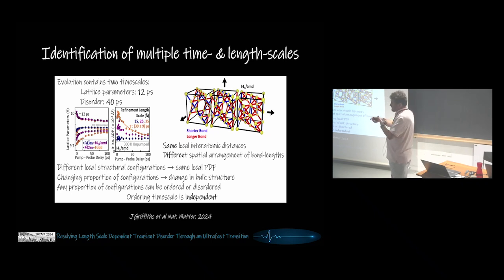So we observe there are probably three time scales, but we observe two because we have missed the third, in the sub-picosecond regime. One is 12 picoseconds. That is essentially the evolution of lattice parameters of various models. They all suggest the same time scale. So that's related to there being different local configurations. You could have different configurations pointing in different directions, and that evolves as a function of time. And then it sort of, I wouldn't call it, but let's say locks in after a 12 picosecond time scale. So you get your space group within this time regime.